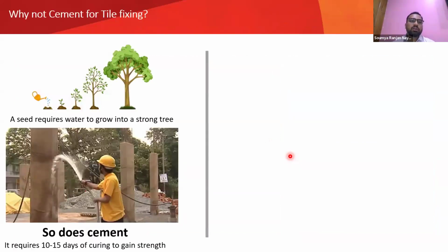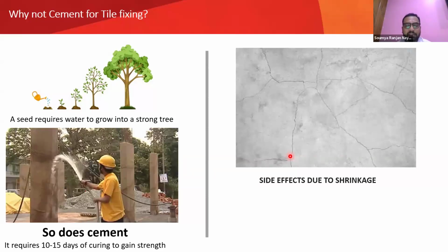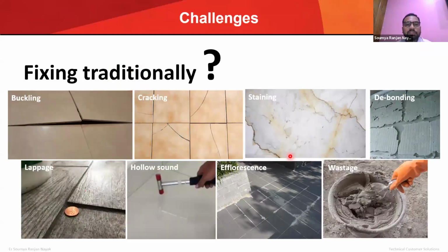So why do we not use cement in tile fixing? Because cement requires curing. When we do a plaster or concrete work, immediately after that we have to do 7 days or 14 days of curing as per the requirement of cement or concrete. If you don't do that, you will not get the desired strength, and in the case of cement, we will get shrinkage cracks. When we fix tile with cement, we will not be able to cure it. So eventually it will lead to shrinkage cracks and other things like hollowness, and we will not get the desired strength and adhesion. That leads to these kinds of challenges.